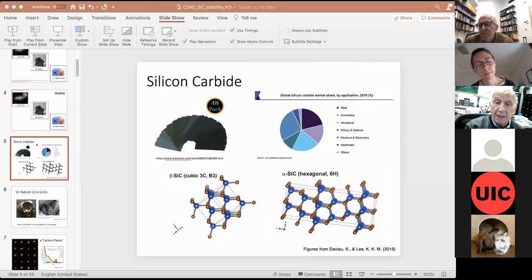There are different ways of saying it. One way is there are very different phonon modes involved, if this were a single crystal to single crystal transformation from one of the diamond phases to the rock salt structure. We actually traced one for a rather different system, which is cadmium selenide. But I think these are fairly strong bonds that are being manipulated, and so it may make a difference. It's not just atoms at random sliding over to the most stable structure. I guess we need to do some experiments and look at these two.